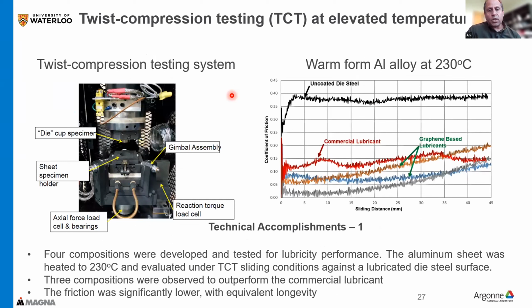So some of the things which are reportable to the DOE, that's what is public, that I'm showing you. So this is a twist compression testing system where you have a cup, you have a specimen, you apply pressure and then twist it a certain sliding distance and then look at the friction coefficient. So this is aluminum alloy at 230 degrees Celsius. And then you can see on your right hand side, this is the commercial lubricants, and this is a graphene-based lubricant that we have developed, that basically outperforms this commercial lubricant.